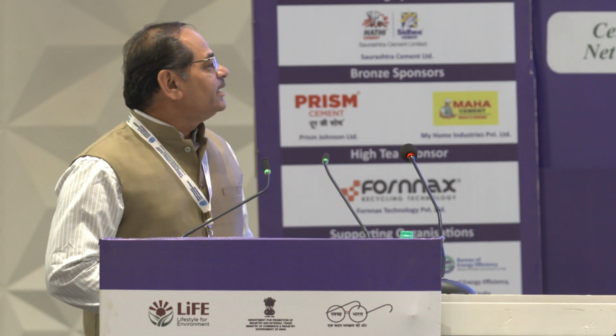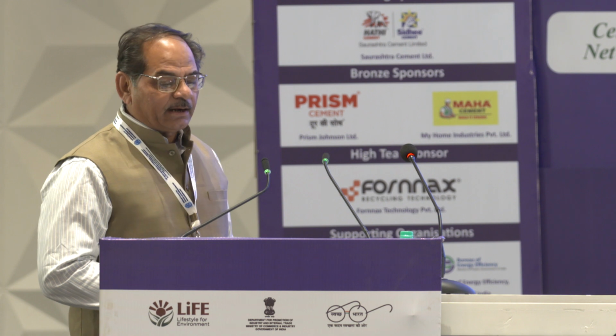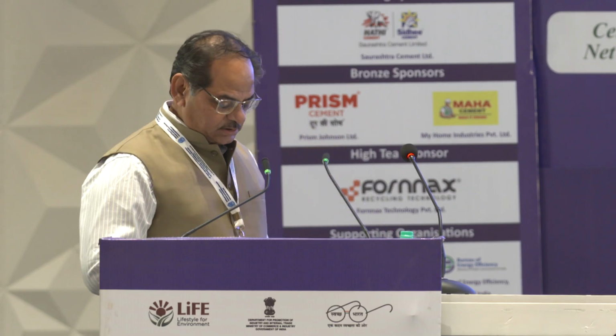So in case of the Marwar Mudwa limestone, it has already high chlorine content. Chlorine content in a cement plant is generally expressed as gram chlorine per ton of clinker. It comes from the limestone, from the fuel, and from the RDF. So in our case, it is 600 to 650 gram per ton of clinker, which is very high.